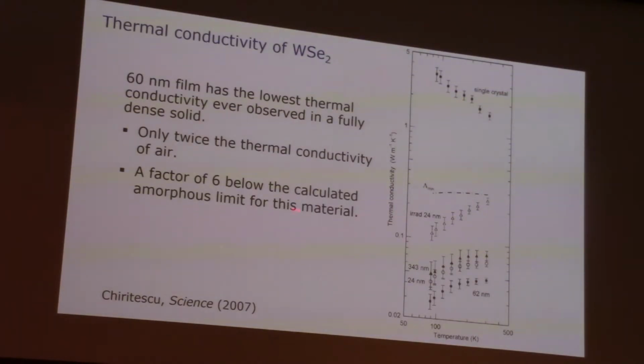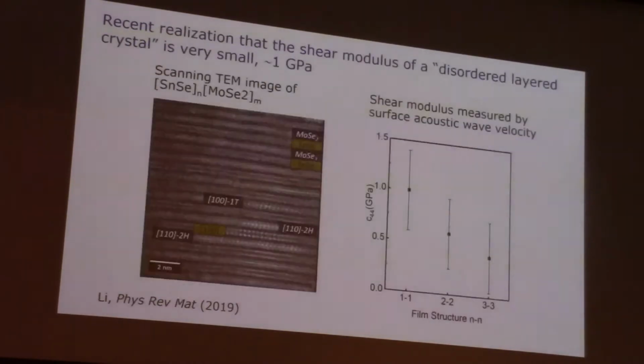So the bottom line is, a factor of 6 or so below the amorphous limit for this material. So we get a material whose thermal conductivity is far below this kind of Einstein-like limit. Okay, well, what's going on? Well, there's a lot of things going on, it turns out, and there's a lot of missteps in the understanding of this. Part of it is the fact that these materials are, of course, disordered. So the phonons scatter off all the disorder involved in the material.